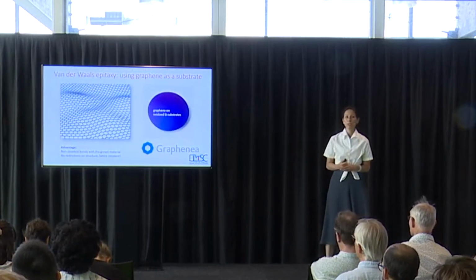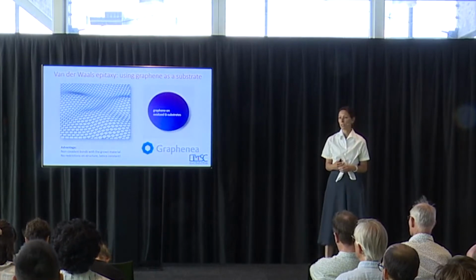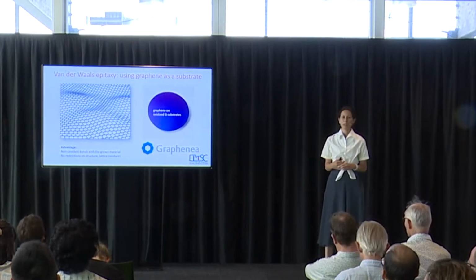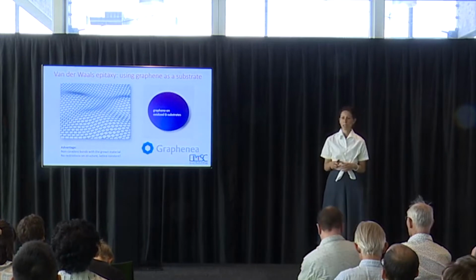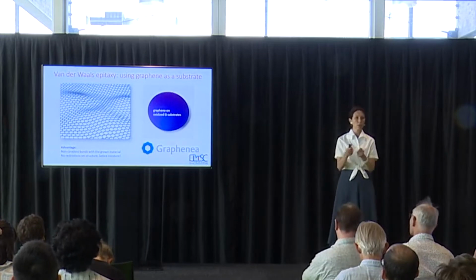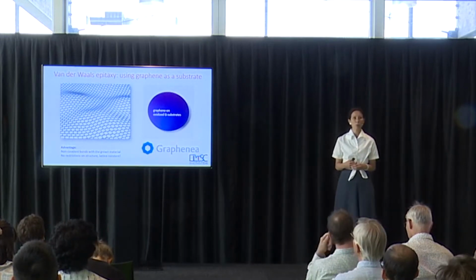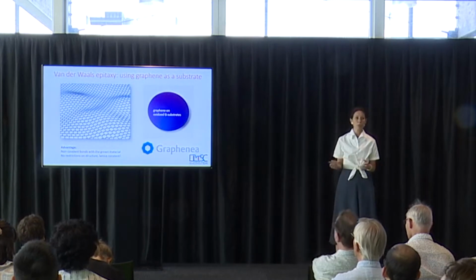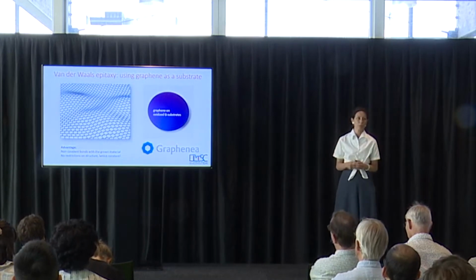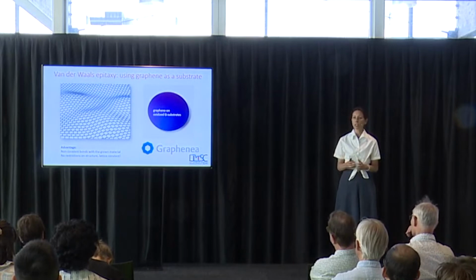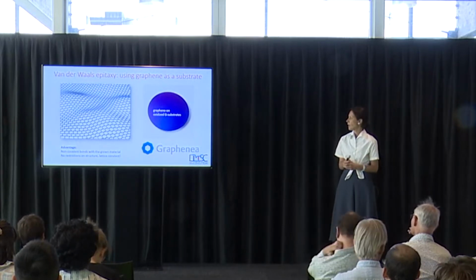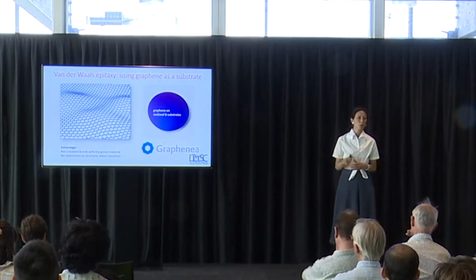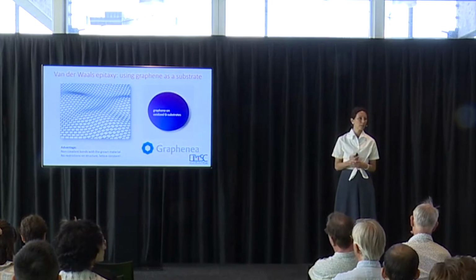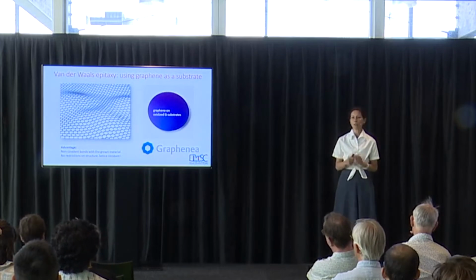So for the growth of graphene, we use commercial substrates because they're relatively cheap now. This is from Graphenea. You can have them on 4 and 6 inch substrate, then you can break your pieces and do your growth. They're reproducible, so you know that each time you have the same substrate. If you do it yourself, it's not clear that your graphene will always be the same. And as you will see, we also buy them because they are not perfect. So they're reproducible but not perfect, and it's good to not be perfect.